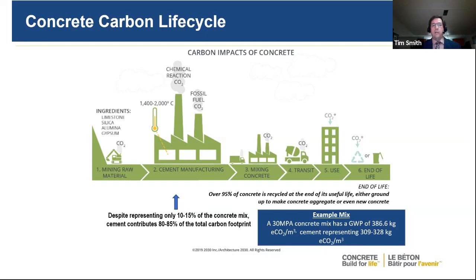The key thing I wanted to point out here: the carbon footprint of concrete is quite low, but 80 to 85% of the carbon footprint of concrete comes from cement, even though it's only 10 to 15% of the mix. So concrete actually is lower, but the cement does have a high CO2 footprint. So as an example, for 30 MPa concrete, you have 386 kgs per cubic meter as your carbon intensity. For this cement, it's around 309 to 328 of that carbon footprint that is actually the cement itself.